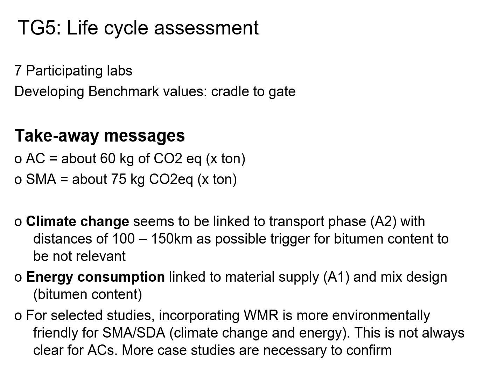They have also seen that climate change seems to be linked to the transport phase of the material, whereas energy consumption is linked more to the material supply and the mix design. So in other words, bitumen content. For selected studies, they have looked at the WMR mixtures that we have used in TG3, and they saw that the stone mastic asphalt and the semi-dense asphalt were more environmentally friendly when WMR mixtures were used in terms of climate change and energy use. However, for asphalt concrete dense mixtures, that was not always clear. And so this work will go on, and they have recommended to do more studies to look at these aspects more.